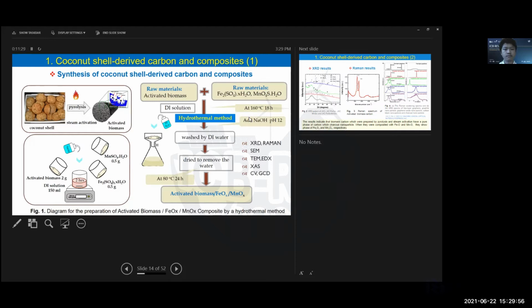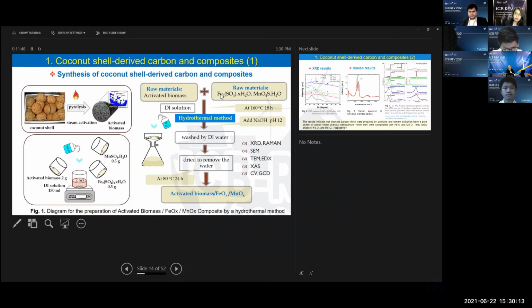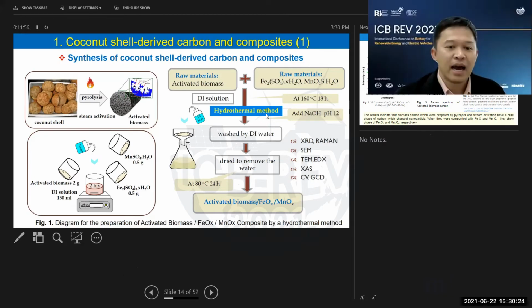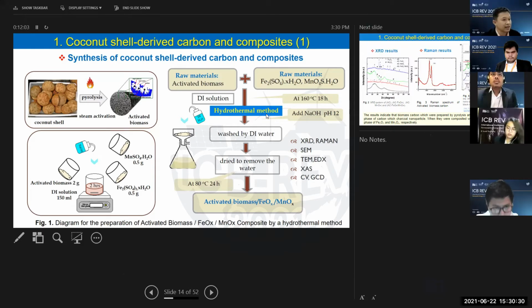For example, if I want to fabricate the composite between the activated carbon with iron oxide or manganese oxide, what I can do is use the activated carbon combined with iron sulfate in case we want to use the iron oxide, right? And we do the hydrothermal process, and then at very low temperature, we can have the composite of activated carbon with the metal oxide of our choice. In this work, we use iron oxide and also manganese oxide, and also combine both metal oxides in the composite system.